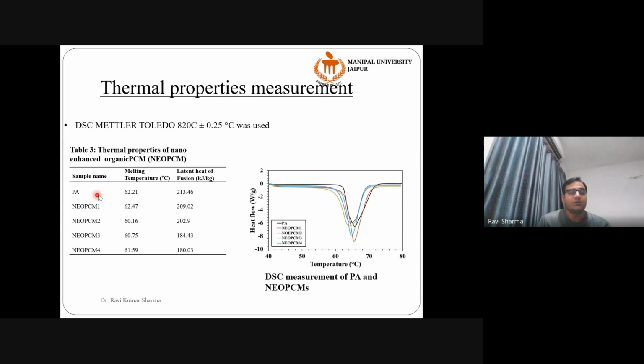The latent heat of pure palmitic acid was 213.46. Once we add these nanoparticles, the latent heat decreases. If we keep increasing the percentage of nanoparticle, the value of latent heat keeps decreasing. This is easy to understand because the specific heat of PCM was high and the specific heat of nanoparticle was low. When you mix these two materials, the net specific heat comes down.